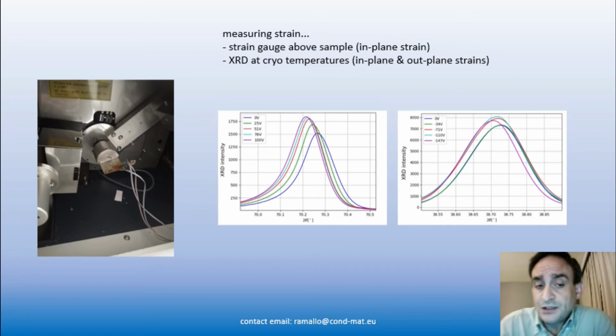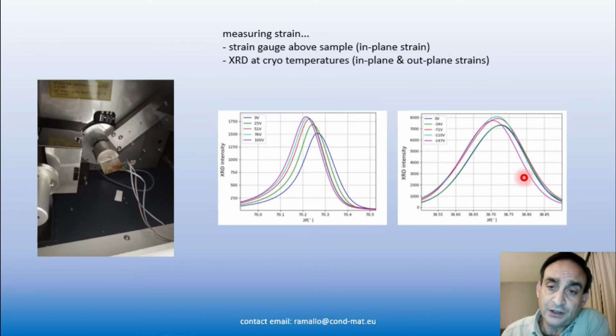So how do you measure the strain you are producing when you do apply the piezo voltage? Well, you may put a strain gauge above the sample. This was the method used by the Dresden group, and you measure with that in-plane strain. What we do is we rely more on X-ray crystallography. So we do X-ray diffractograms at cryo temperature. So we cryogenize the sample space, and as you see in these peaks, you can actually see the displacement of the peaks as you apply the piezo voltage, and this gives you both in-plane and out-of-plane strains.